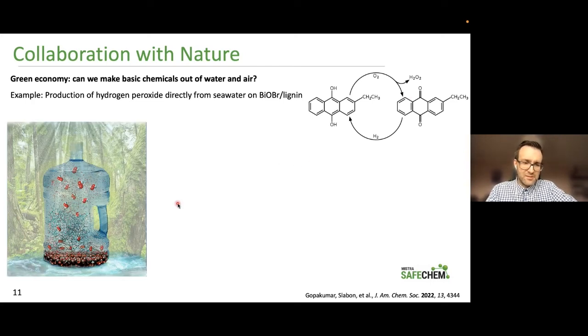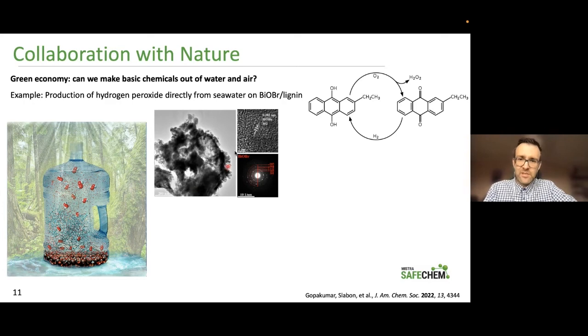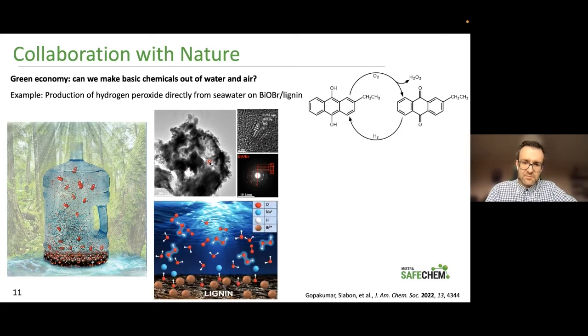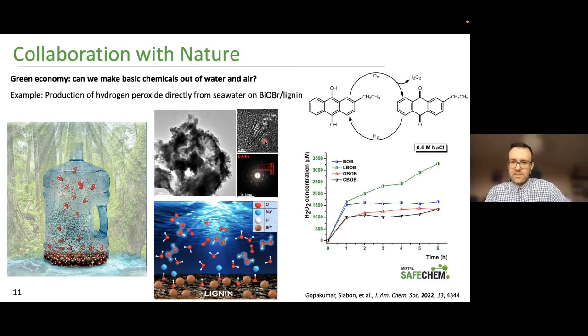We want to get hydrogen peroxide on a lignin-supported catalyst. And for this, in this case, we need particles, like this bismuth oxygen bromide, 111 system. You can see such nanosheets, and we are growing them directly on lignin. Here you can see the catalyst with lignin as support. And what we get is quite amazing, because only with the lignin as support for these nanosheets, we can get the best performance. Here's a graph.